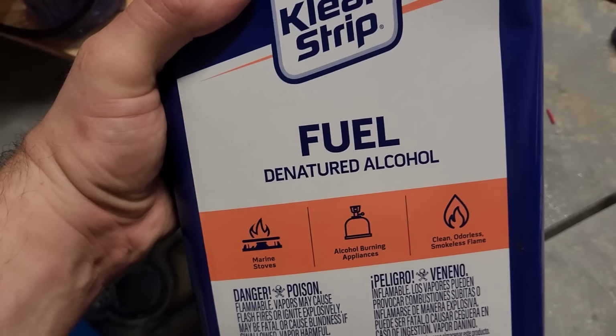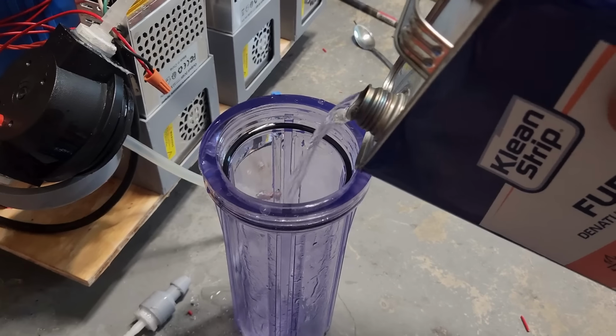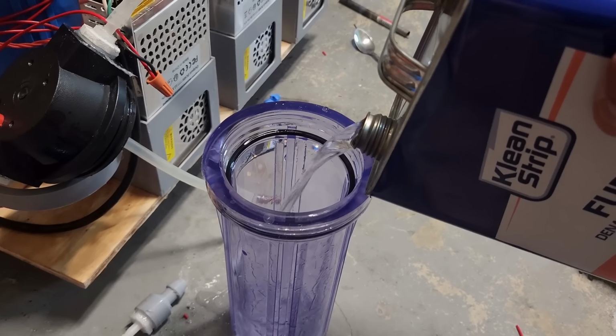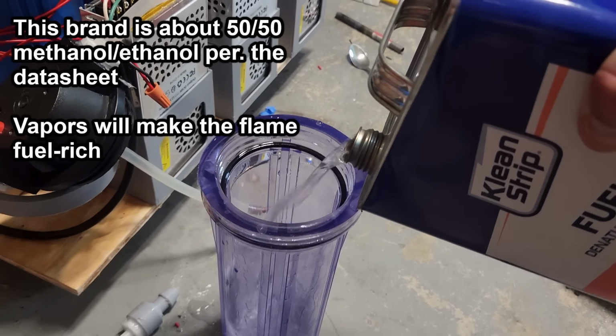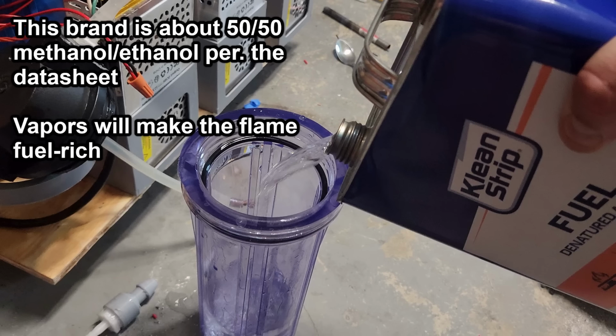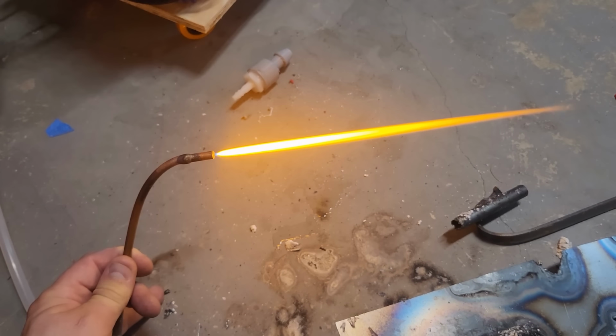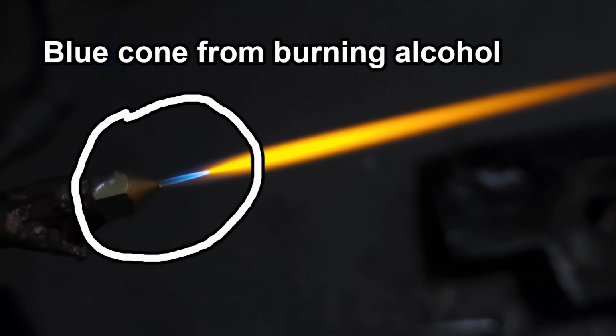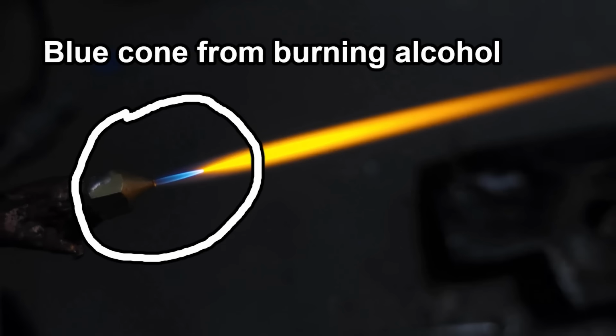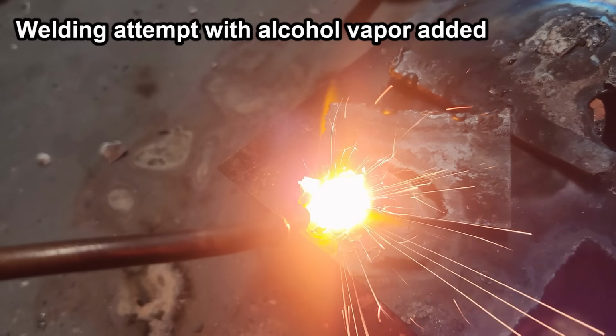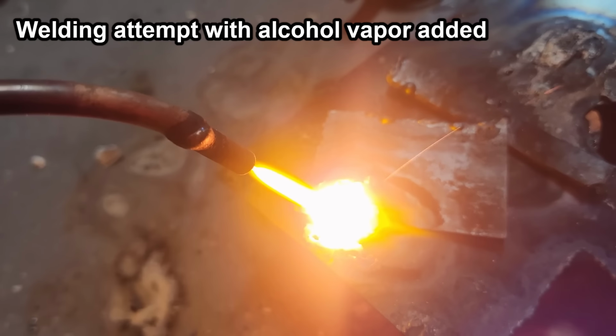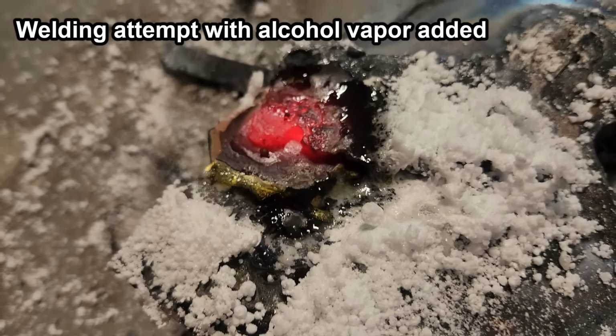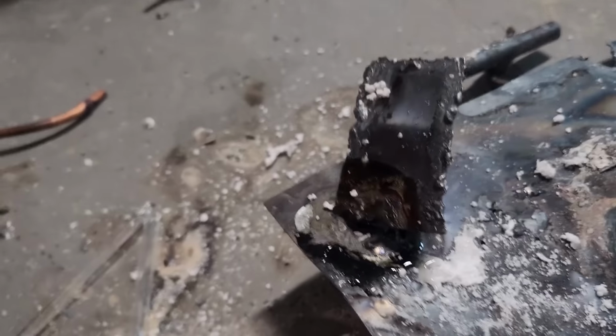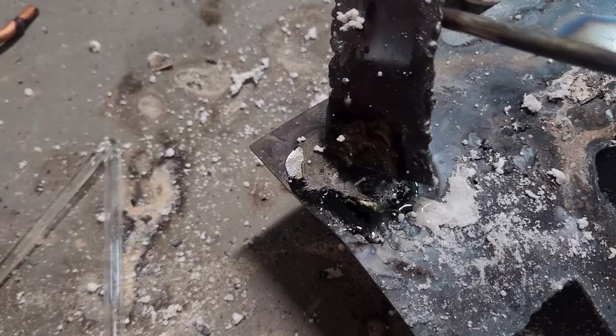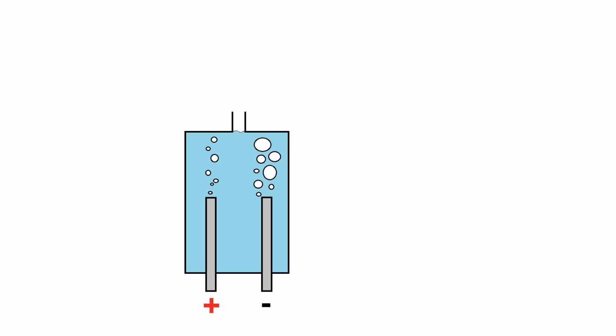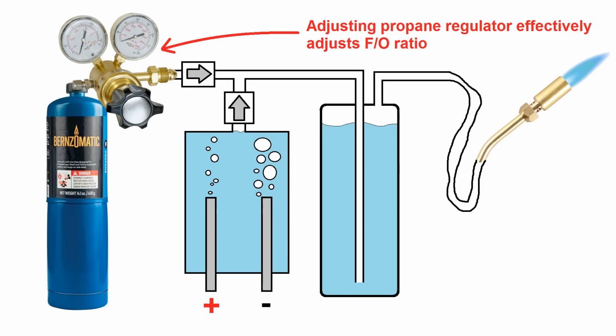I replaced the water in the bubbler with some denatured alcohol in order to make the flame a little bit more fuel-rich by adding the alcohol vapors into the stream and hopefully avoid oxidizing the steel. The flame was noticeably larger and brighter, and I got this little blue cone at the nozzle output after the alcohol vapor was added to the stream. The weld joint was still mostly slag, with the exception of one little spot where this piece of steel actually didn't manage to stick. To make this really work right, the HHO will probably need propane injected into it.